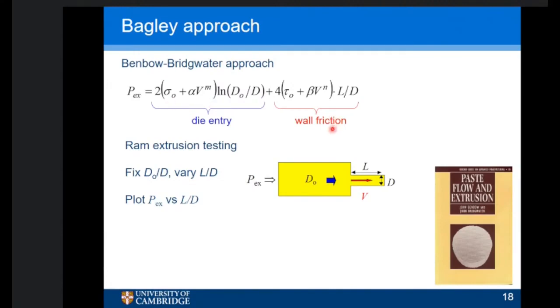And then along the die, we say, well, we have a flow with a wall shear stress, and it's related to L over D. So what you do is you fix this bit by just keeping D0 over D constant, and you change L over D. And then you plot your extrusion pressure against L over D, and the gradient will give you the wall shear stress. And that is effectively a Bagley plot. You'll find it written slightly differently in the polymer literature, but that's what you do. You change the length of the die, and you find the change in pressure, and that gives you your wall shear stress. So it does require a few experiments, though.